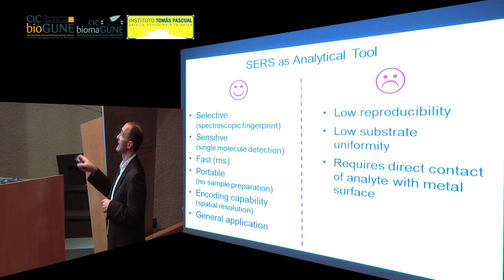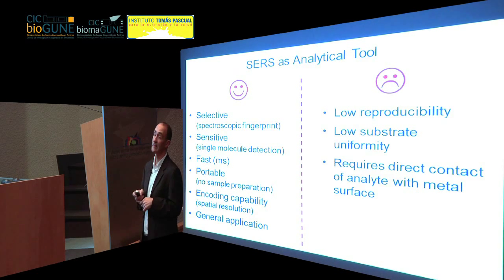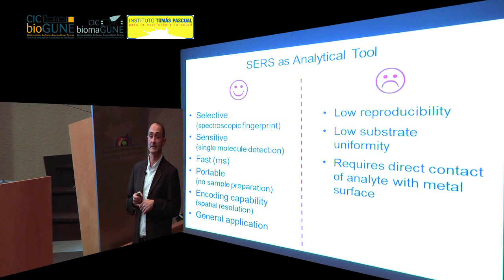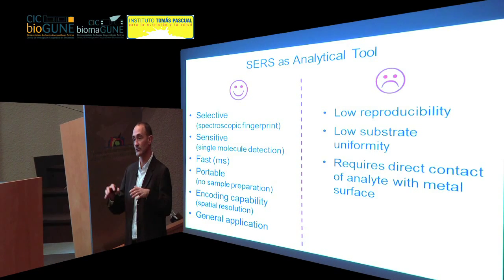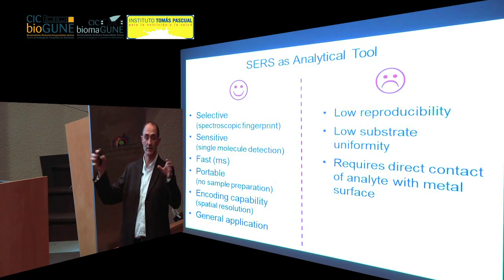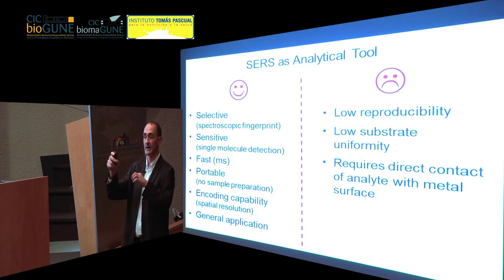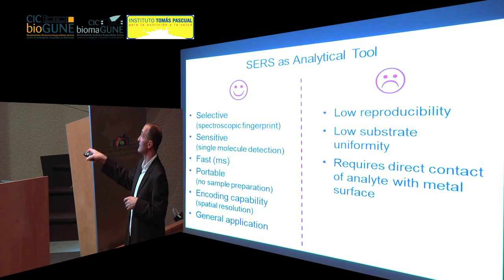The problems that have so far restricted the application of SERS are the reproducibility of the signals, because normally you try to enhance the signal so much that you need to aggregate the particles. And if you are not careful enough, every aggregate will be different, so the enhancement will be different. And this also affects the uniformity of the substrates.